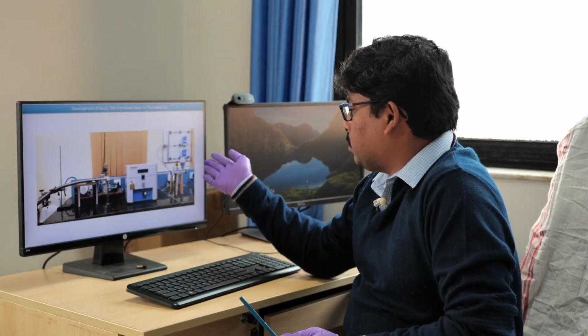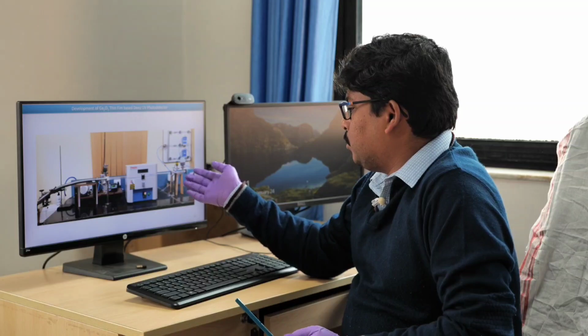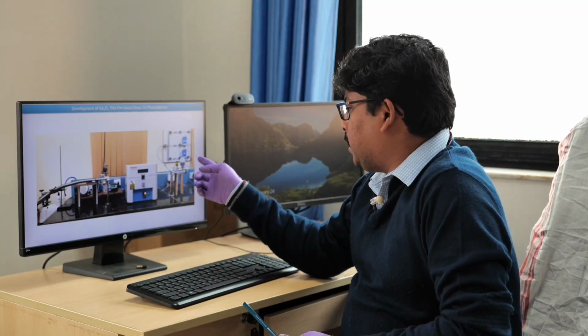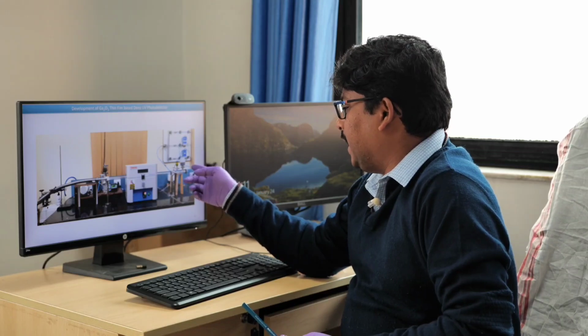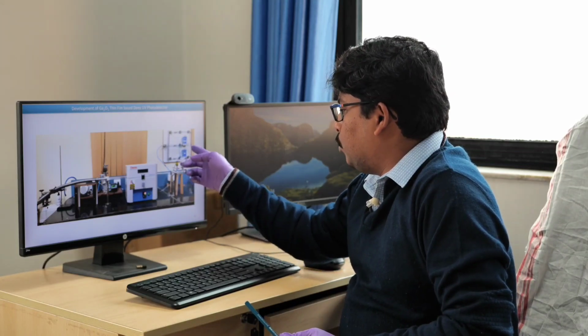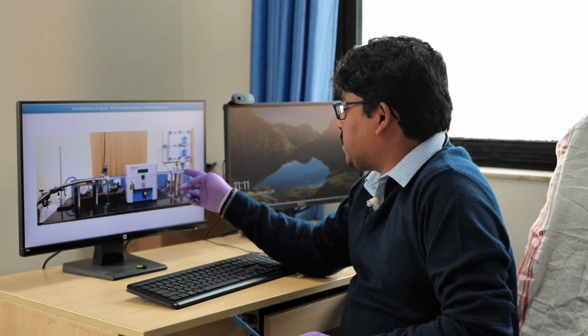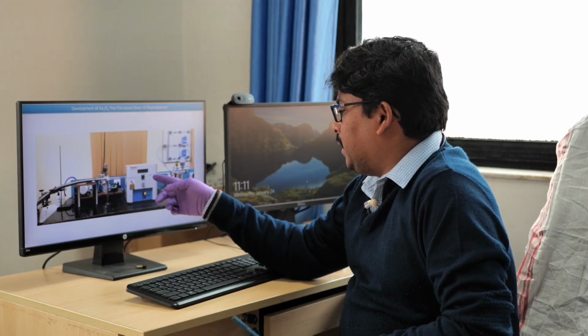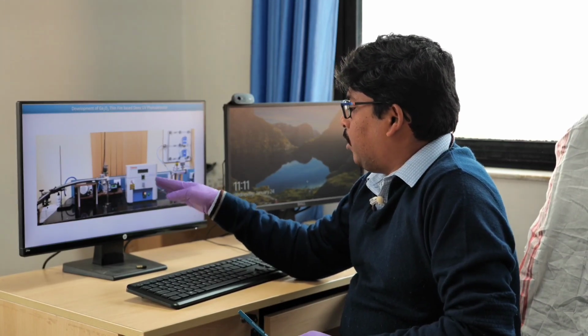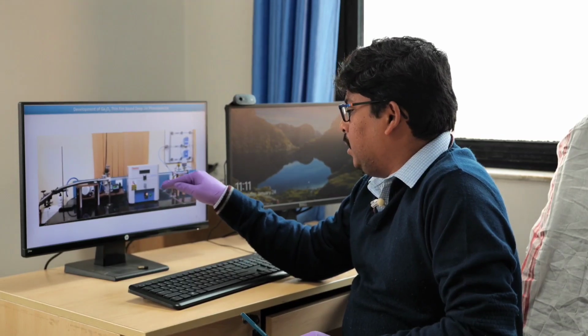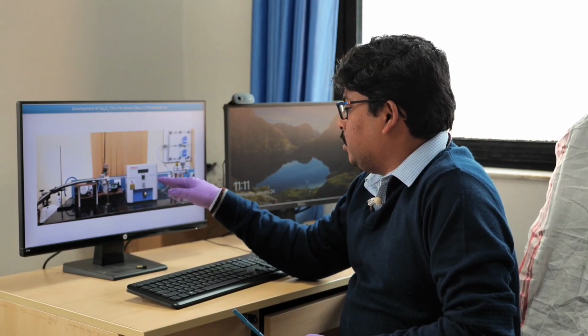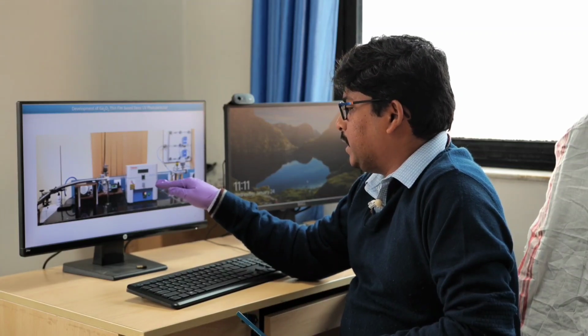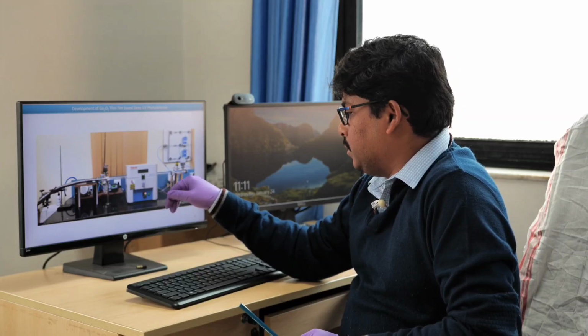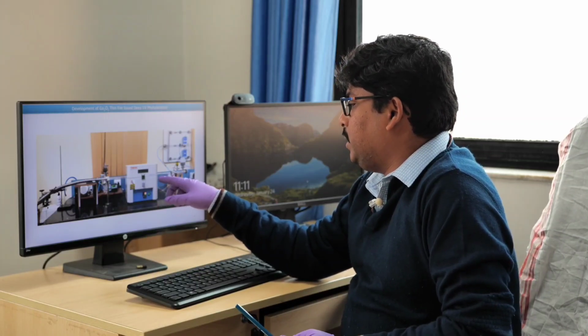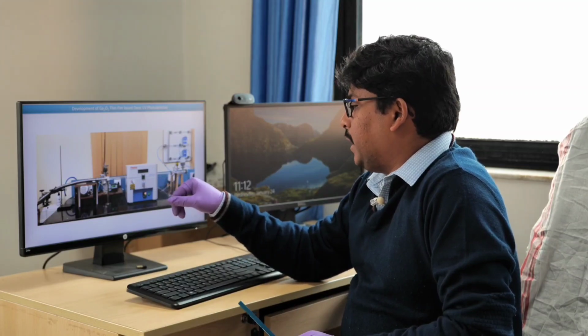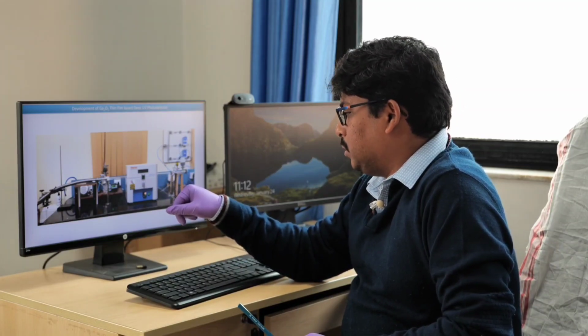So this oxygen is another precursor to develop this gallium oxide material, but we also use argon as a carrier gas. Both argon and oxygen gases are coming through these MFCs, and inside we have this gallium metal itself as a precursor, and on top of this gallium metal, along with some other arrangement, we kept our substrate, and the substrate is the sapphire we used for this particular study. Initially we got the undoped gallium oxide thin film on the sapphire substrate.